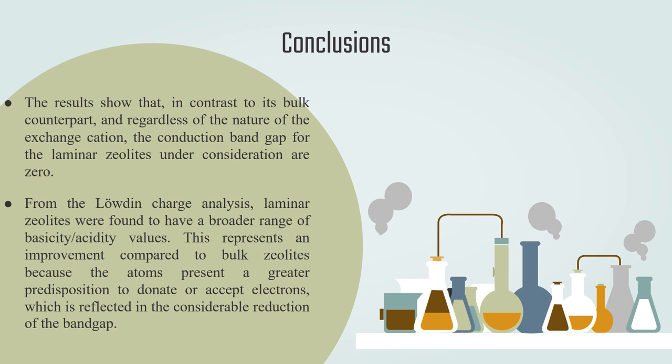Conclusions. The results show that, in contrast to its bulk counterpart, and regardless of the nature of the exchange cation, the band gap for the laminar zeolites under consideration is 0. From the Loewdin charge analysis, laminar zeolites were found to have a broader range of basicity-acidity values. This represents an improvement compared to bulk zeolites because the atoms present a greater predisposition to donate or accept electrons, which is reflected in the considerable reduction of the band gap.